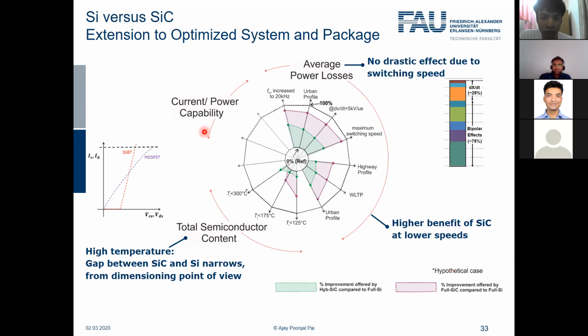So now what we do is we check the current or power capability of the module, meaning that for a given module size, can I draw 300 ampere from the module or can I draw 500 ampere from the module? It's best when the module can give me more current capability. Understood. So at 400 volt, silicon carbide can give roughly, let's say, 25% more current capability. But when I go to 800 volt, this goes up to roughly 60% or even 65%, which means the benefit of silicon carbide is much higher at 800 volt.